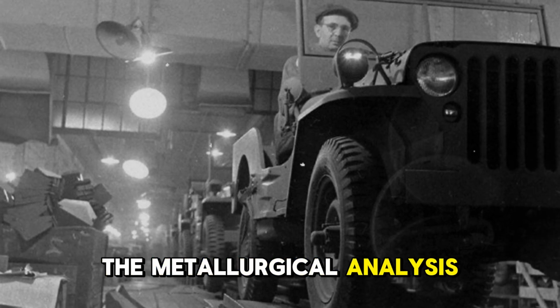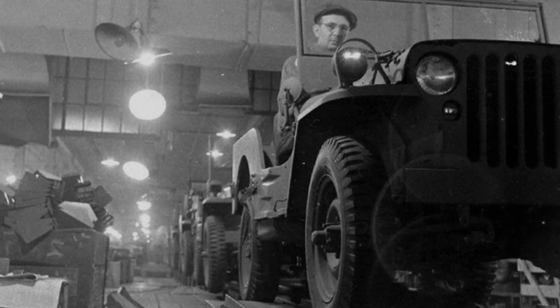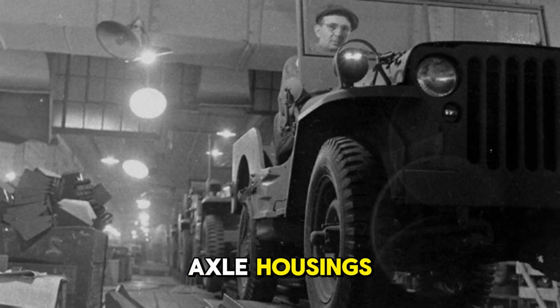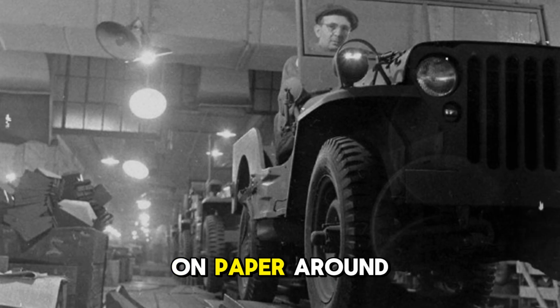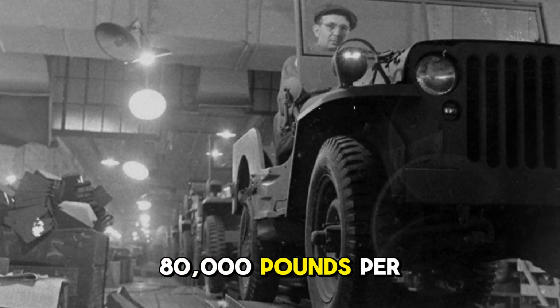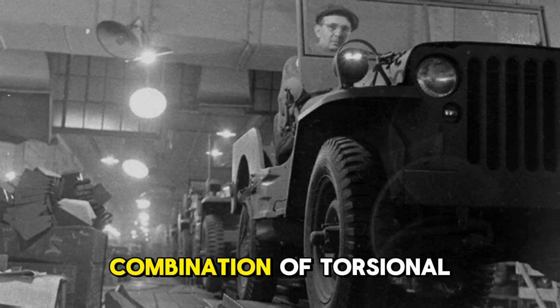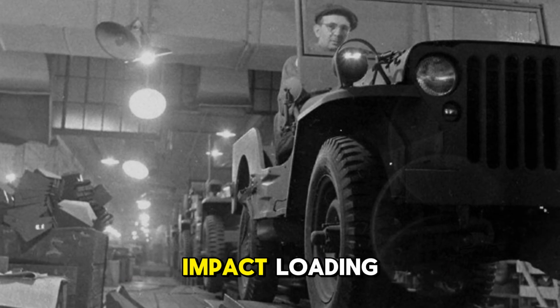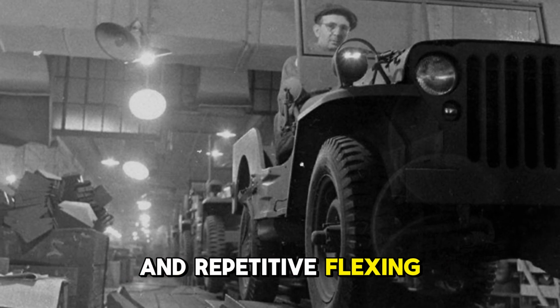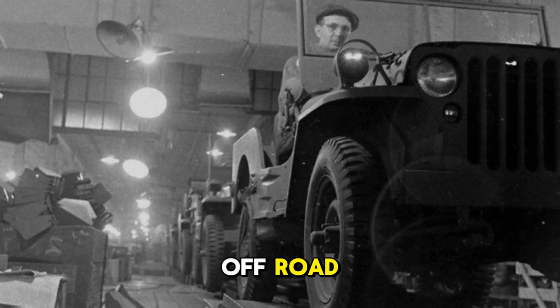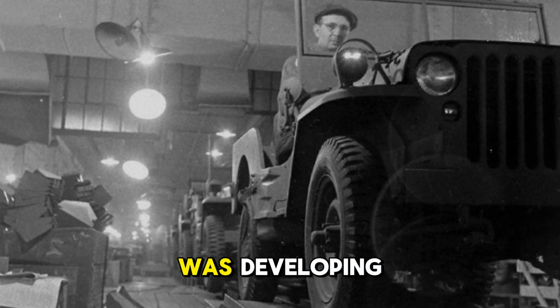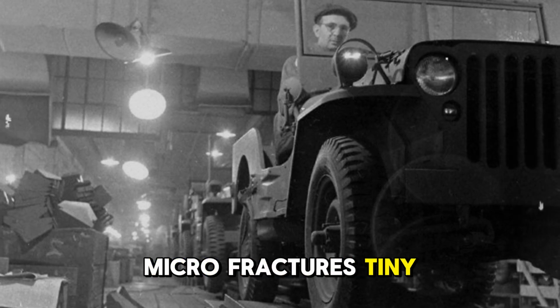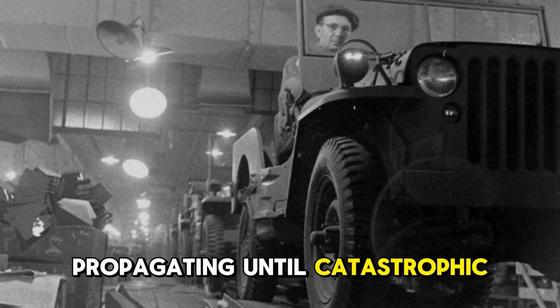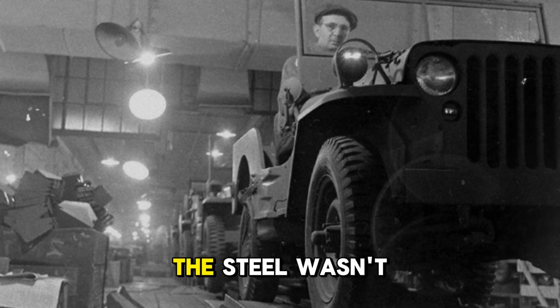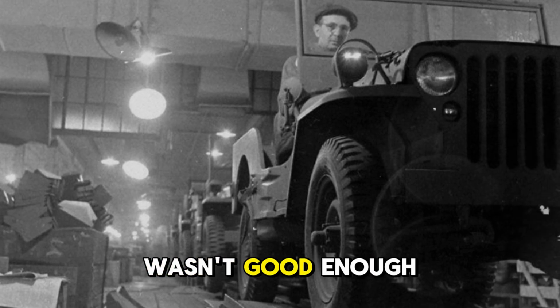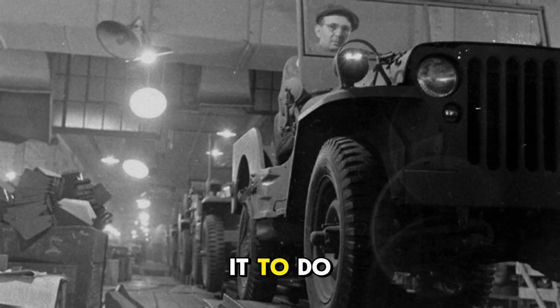The metallurgical analysis came back 3 days later. The carbon steel used in the axle housings had adequate tensile strength on paper, around 80,000 pounds per square inch. But under the combination of torsional stress, impact loading, and repetitive flexing that Jeeps experienced off-road, the crystalline structure of the steel was developing microfractures. Tiny cracks propagating until catastrophic failure occurred. The steel wasn't bad, it just wasn't good enough for what the military was asking it to do.